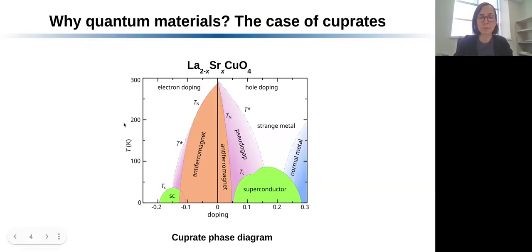So this is a typical phase diagram of a cuprate. I have doping here, which is essentially the amount of strontium you introduce. And then you have temperature on the other axis. And as you can see, when you vary the doping and the temperature, you can tune your system into a variety of very different, not fully understood quantum phases, including the pseudogap, strange metal, and of course the superconducting phase.